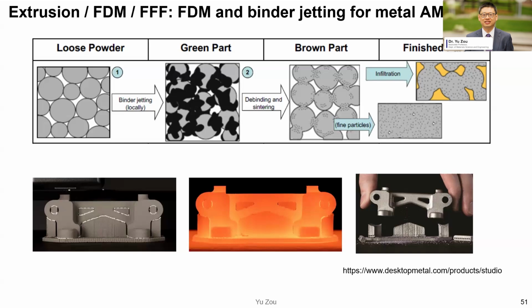The advantage of this method is there's no laser, and the system is relatively simple. The cost is relatively low, and also there are fewer safety concerns regarding lasers. The porosity of this part is relatively higher than some parts made by laser-based additive manufacturing. And for some parts, it could be a problem, for example, the fatigue property is really sensitive to porosity. But if this is a part not very critical for fatigue, I think that could also be a good method to reduce the cost.